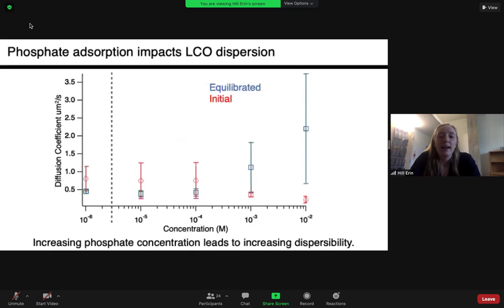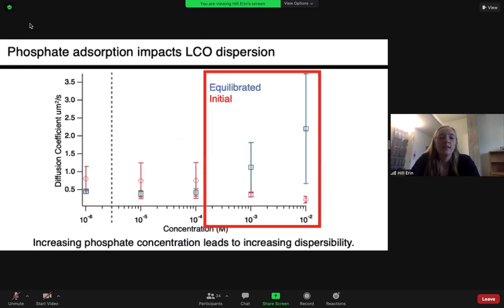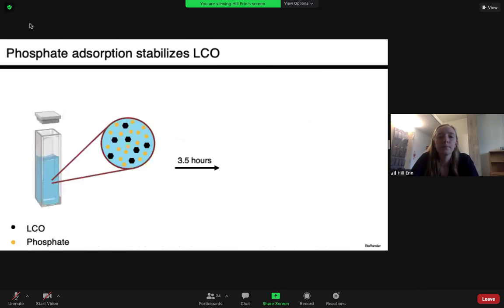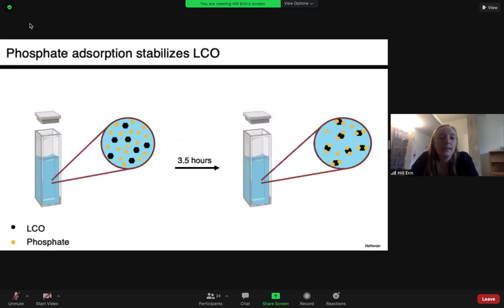So we can see that at the 2 highest concentrations of phosphate, the diffusion coefficient of the equilibrated solutions is greater than the initial measurement. The larger diffusion coefficient suggests that there are smaller nanoparticles in solution, which, when coupled with that zeta potential data, means that increasing the phosphate concentration may cause more stable dispersed colloidal suspensions due to the electrostatic repulsion. And so this image just depicts what's happening. When LCO and phosphate are mixed together, we then see phosphate bond to the LCO, and the nanoparticles remain dispersed and stabilized throughout the solution.